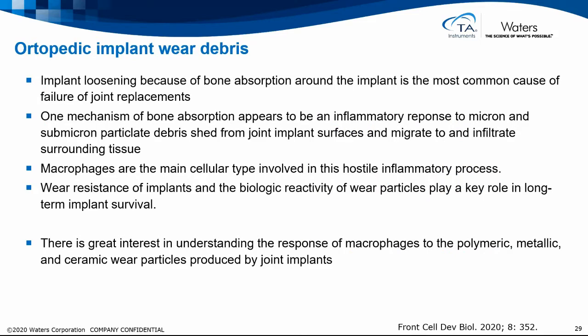Another example is implant loosening because of bone resorption around the implant, which is the most common cause of failure of joint replacements today. And one mechanism of this bone resorption appears to be an inflammatory response to small particle debris that is shed from the joint implant surface and then migrates to and infiltrates the surrounding tissue. Macrophages are the main cellular type involved in this inflammatory process. It is important to get wear resistance of implants, but it's difficult, and also to control the biological reactivity of this particle debris. They will play a key role in the long-term implant survival. So there is a great interest in understanding the response of macrophages to the polymeric, metallic, and ceramic wear particles that are produced by joint implants.